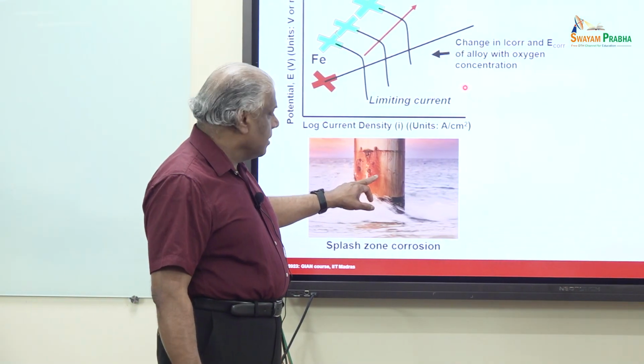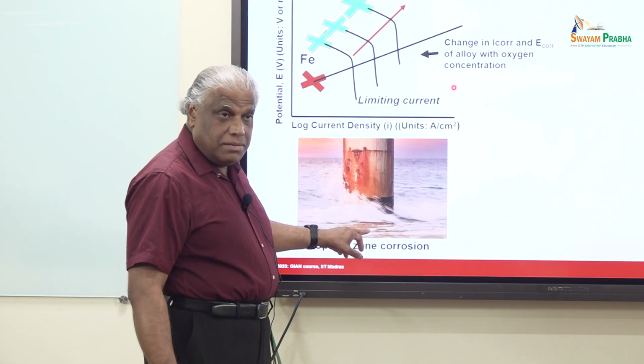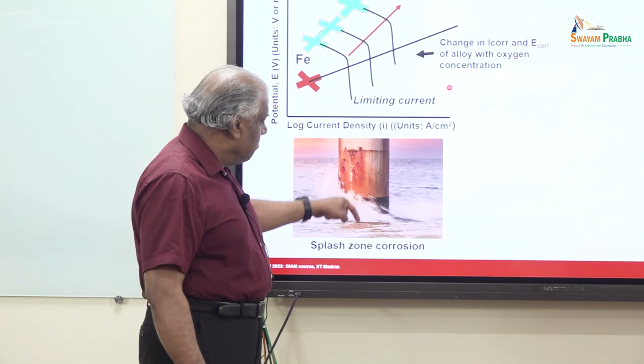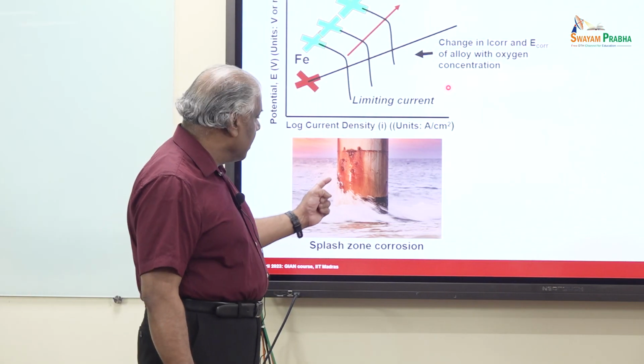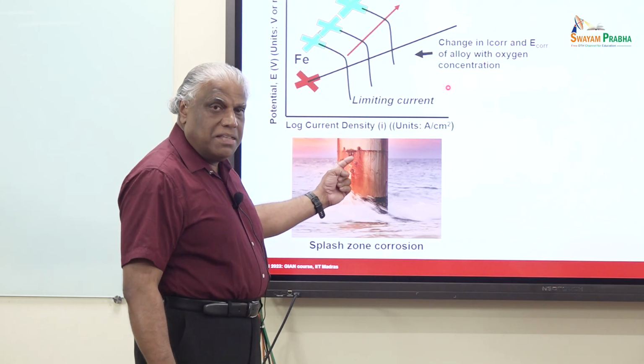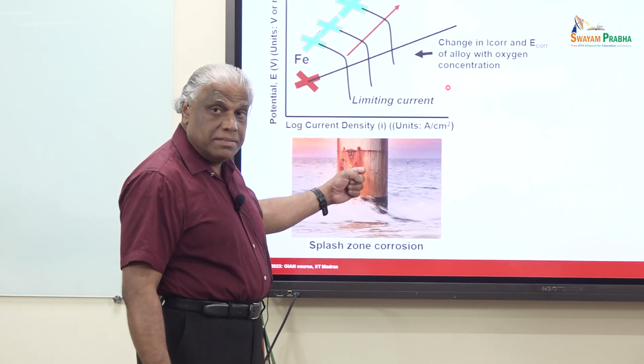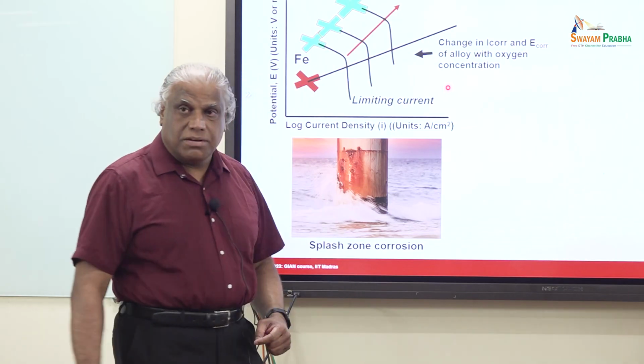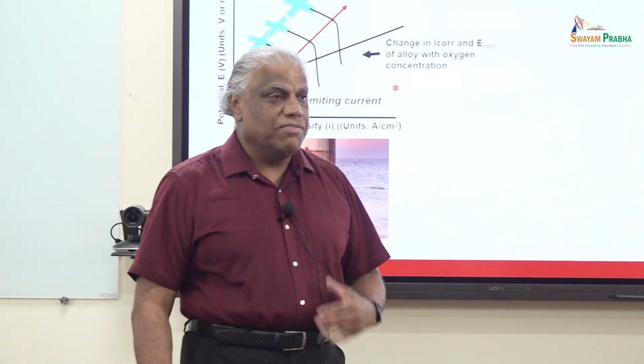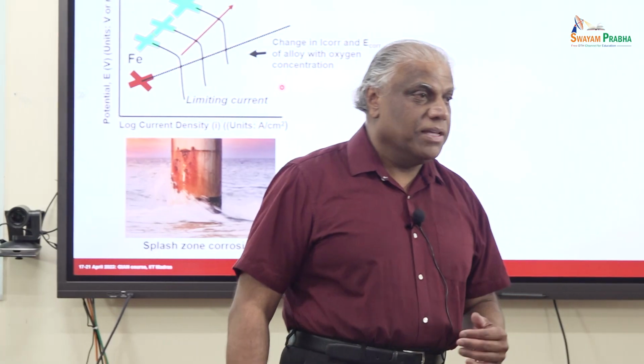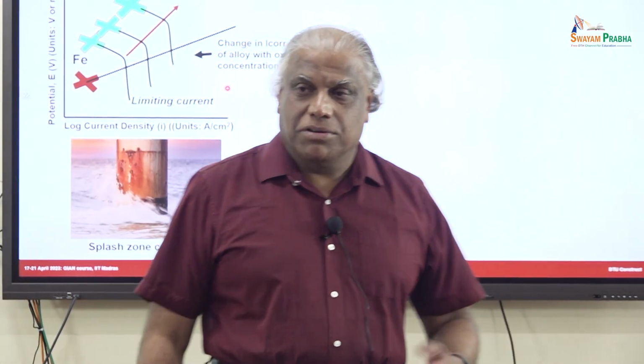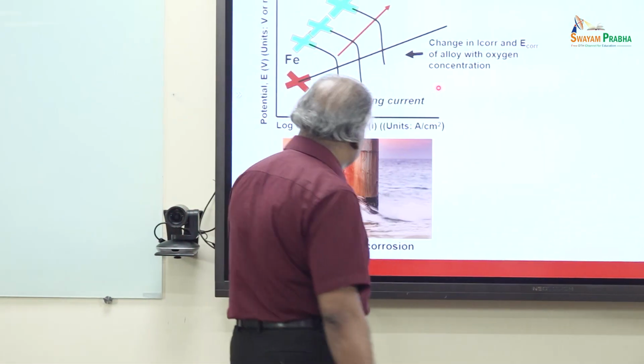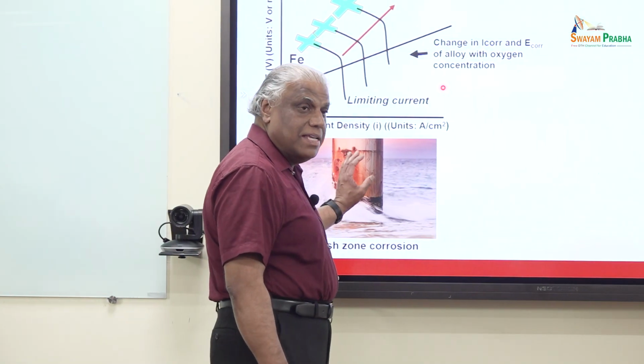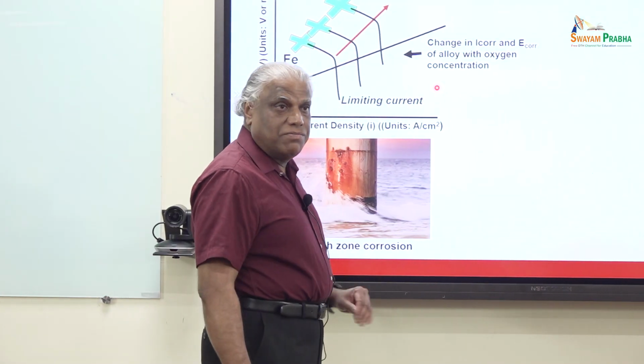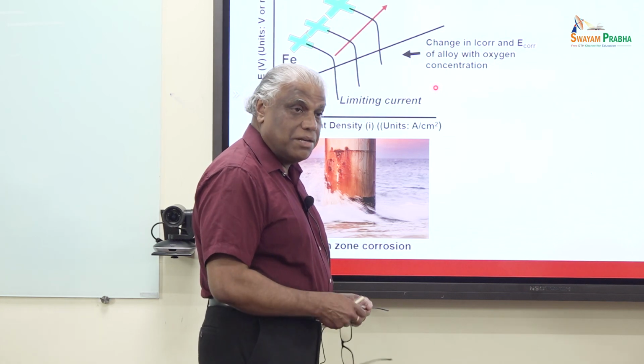When the wind turbine is in the sea water, they are not worried about the corrosion below the water. They are worried about the corrosion here. This is the place they put the heavy duty paint, because this is the place where they see the corrosion problem, because that's the area where the sea water is splashing. They call it a splash zone, and there you have the corrosion problem, because oxygen is always replenished here very easily, and you can have a higher concentration of oxygen, and you can have a higher corrosion rate. So there you can see the importance of this.